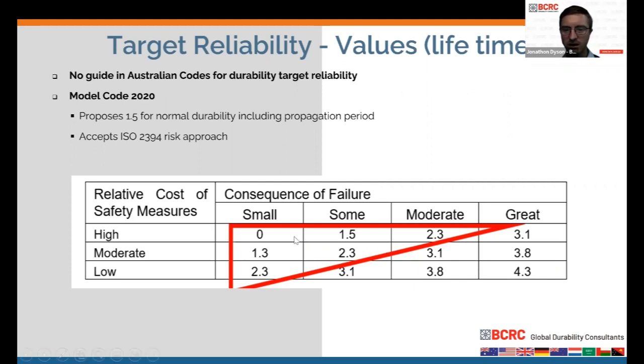And so just another table here, which highlights that if you're talking about the consequence of failure, of some outcome that might occur, it could be small, it could be moderate, it could be extreme. And also, it's inevitable that the relative cost of safety measures also comes into play. So if you have, for example, something that is a small consequence if a failure occurs, and it's a low cost to implement safety measures, well, then you might say, let's go for a reliability of 2.3 in that case, which is a reasonably high reliability, because even though the consequence of failure is small, it doesn't cost much to actually implement those safety measures. But if the cost of those safety measures is high, then you say, the consequence of that happening is pretty small, it's quite expensive to implement extra safety measures. So we'll go for a reliability of zero in that case, and we'll base our design on that.